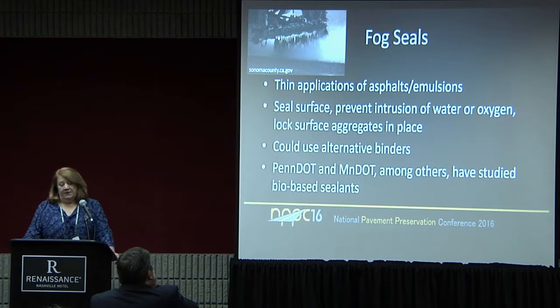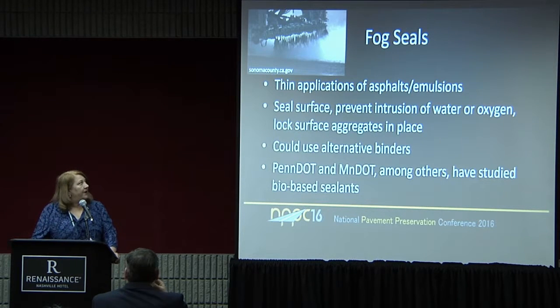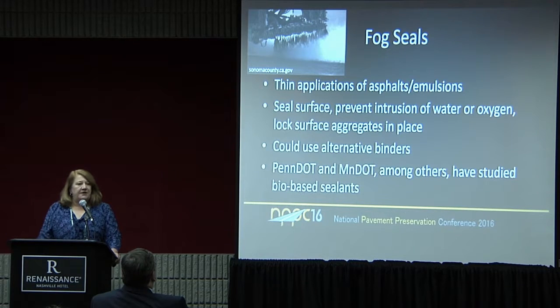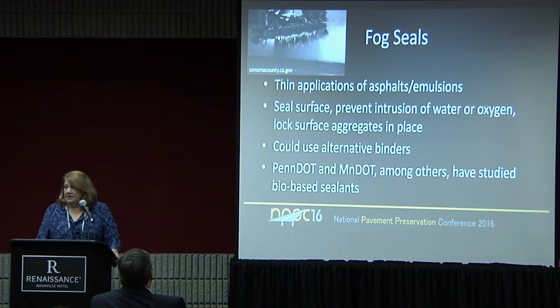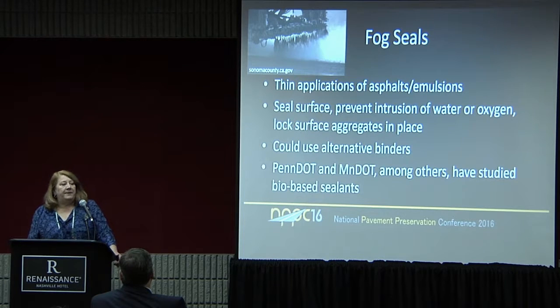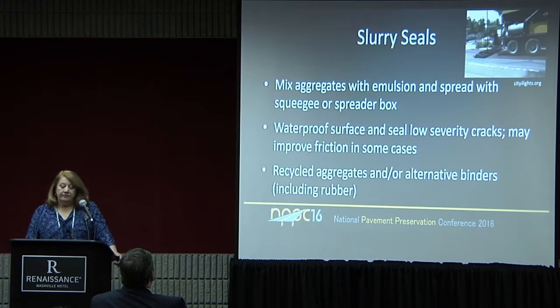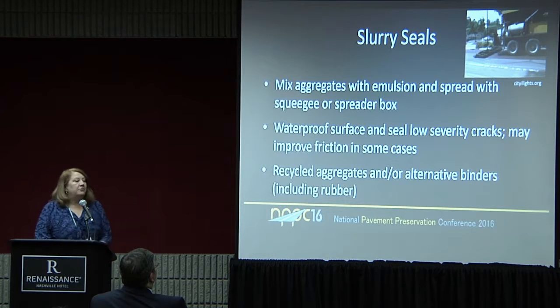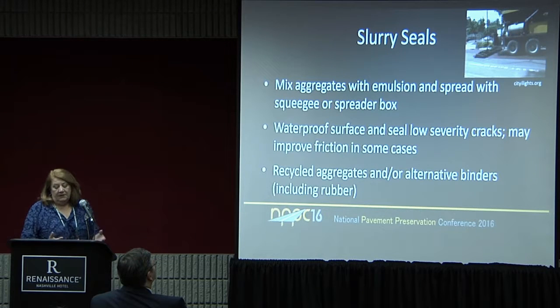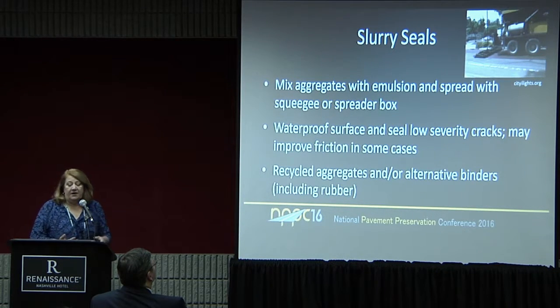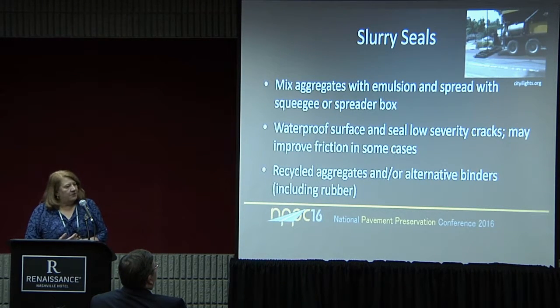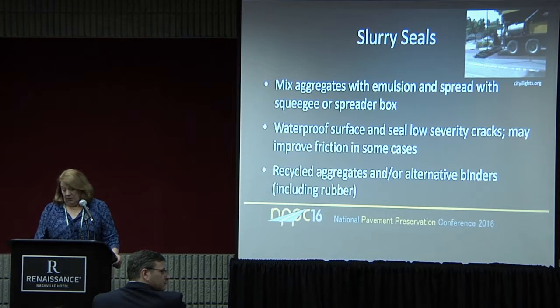Fog seals, we're not putting new aggregates on the roadway with a fog seal. We're just locking the surface aggregates in place. But again, this is a place where you could use some of the alternative binders. And in fact, Pennsylvania DOT and Minnesota DOT, among others, have studied the use of bio-based sealants in these applications. Slurry seals, you use both aggregates and binders, again, to waterproof the surface and seal some low severity cracks. Depending on the aggregates you use, you can improve the friction as well.